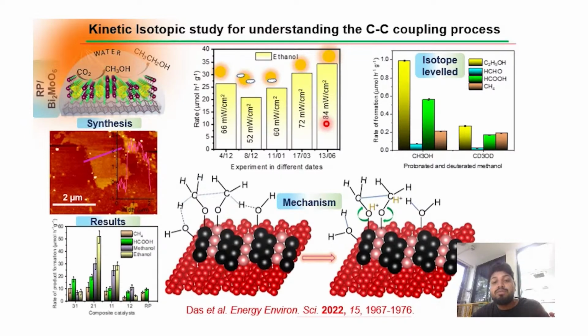Later, our motto was to understand why ethanol formation is happening in this particular kind of catalyst. And from primary kinetic isotopic studies, and from different control studies, like feeding methane and methanol, we have proved that an OCH3 kind of coupling reaction is happening, which we again proved when we employed deuterated methanol. We found these hydrogens are deuterated. However, these hydrogens are normal protons. From there, we proved it is an OCH3 kind of coupling reaction.